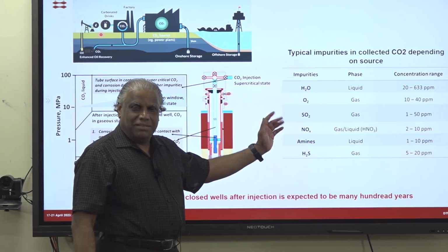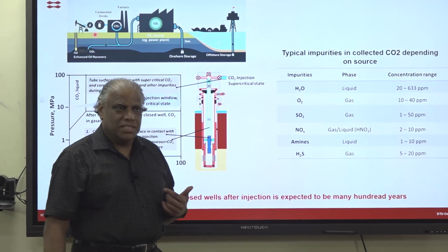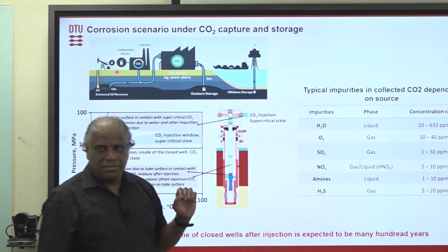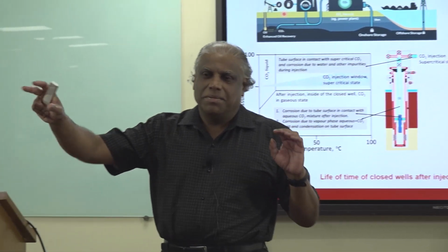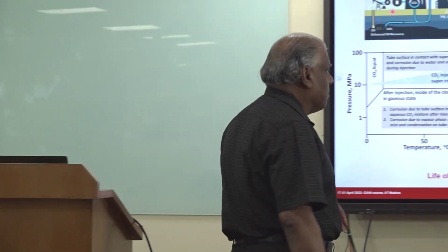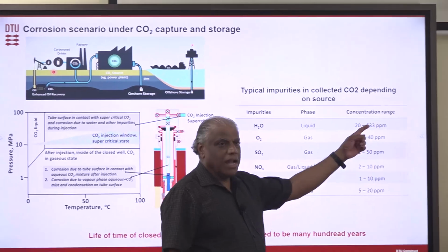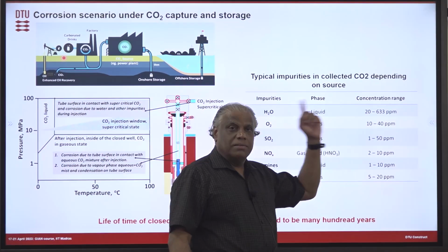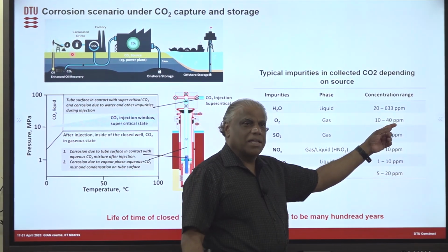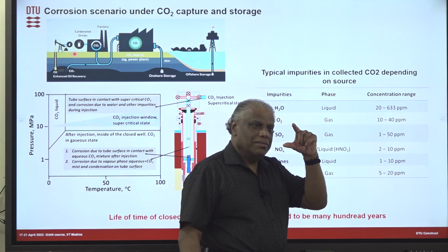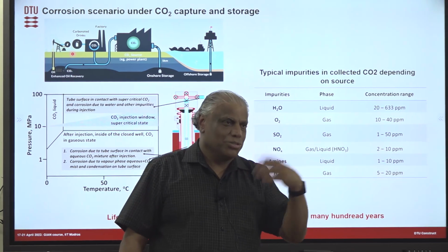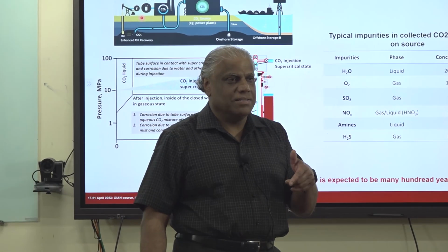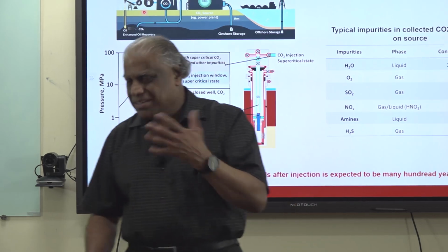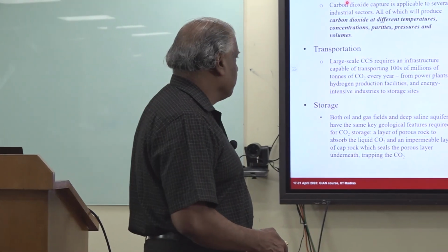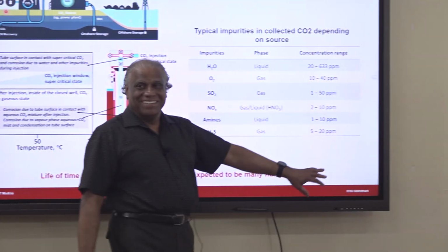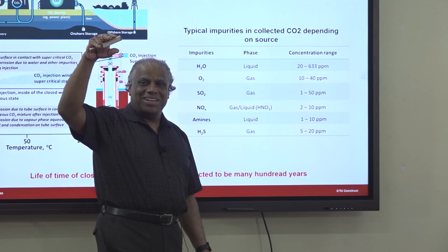We can also look at it another way. They call it a sensitivity analysis. Sensitivity analysis means today you think that they collected CO2 from this place. Tomorrow they collected the CO2 from a cement factory. When they collect the CO2 from the cement factory, they found that the SO2 level is 100 ppm. If they have a model, they can put this contamination into the model and say that, okay, even if it's 100 ppm, the corrosion rate will increase only 10%. It doesn't matter. You can also inject it like that. So that's called sensitivity analysis. So you can also use a model for the sensitivity analysis. This is the kind of rough idea to come up with. Good question. You can remove everything, but then the CO2 injection costs become very high.